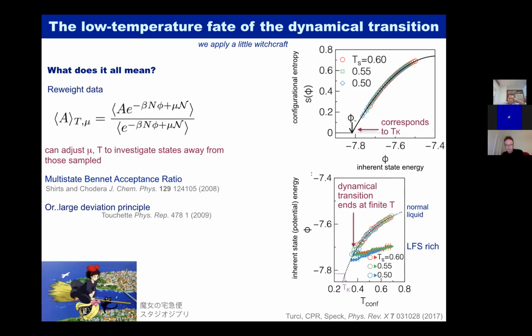We see this gets very low. The system is going to very low energy states. The bottom graph on the right is closely related to the original Kauzmann plot. We have a low energy, local structure rich state on the bottom, and the normal liquid on the top, and they approach one another at a finite temperature. The quantity we're looking at here is the inherent state energy. So we have two of these dynamical phases in the dynamical phase transition of facilitation, and they approach one another in a way which, as I'll show in a minute, looks rather similar to the original Kauzmann plot.